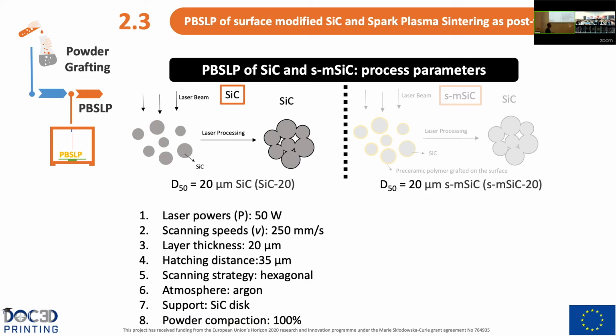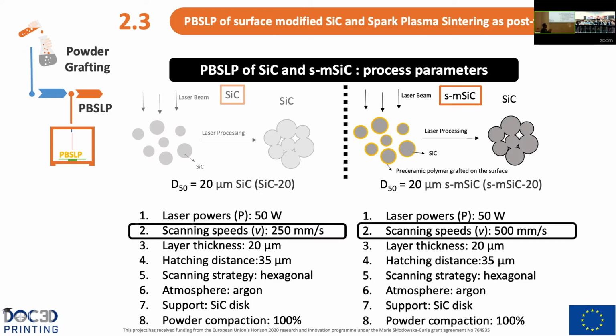So regarding the parameters that we use for the silicon carbide to do this comparison, here are some of the parameters, and maybe you're asking why we are using 50 instead of 45 as we used in the beginning. Actually, we can discuss after, but at this point, we didn't start yet the collaboration with the colleagues from Turkey, and we have this value as the best one for the process. And comparing the surface modified silicon carbide, here we have exactly the same parameters, except for the scanning speed, where we are using 500 instead of 250.